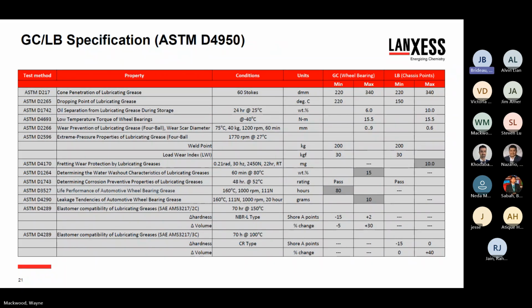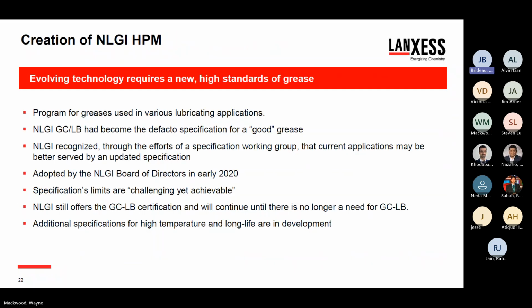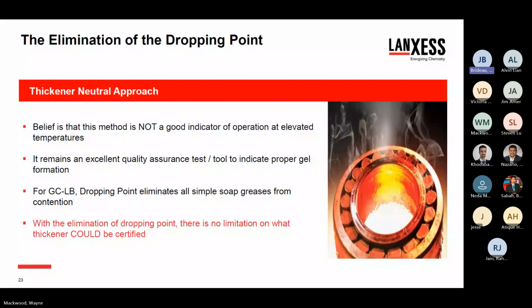When you see the HPM spec, we have removed the dropping point. So the HPM spec is potentially achievable by any thickener type, as there is no dropping point spec as part of it. The reason is that we've had a lot of discussions internally. The steering committee and others have come to the determination that the dropping point is not the best indicator of operation at elevated temperatures. It is a good quality assurance tool, but it's not an operability tool. There are better ways to measure it, and we've removed it.